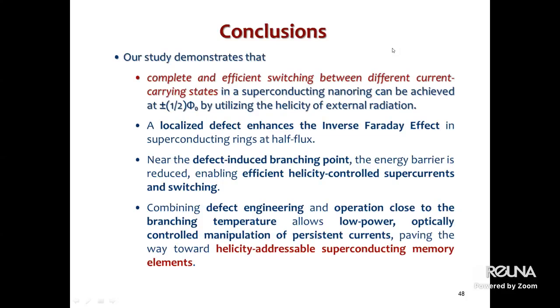Either we work very close to TC, and that's not so interesting because very close to TC we have a lot of fluctuations, and exactly in that region we have a destruction of the switching effect. But if we go below the branching point, which depends on the strength of the defect, it can be 0.8, it can be 0.9, so it's quite deep inside the superconducting state region, then the switching is recovered again, and moreover, it provides some advantages, and one of them is that the switching time increases. So in any situation, if we are below the branching point, switching is present.